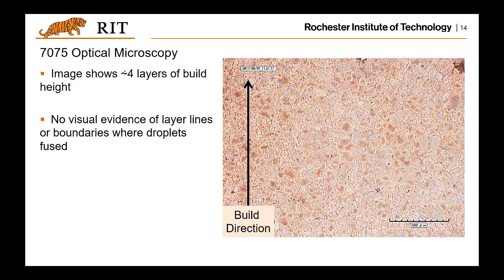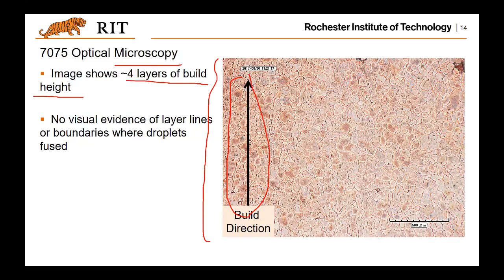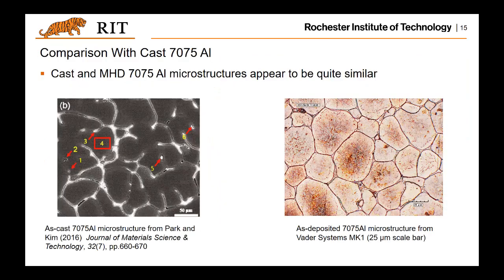And if we look at the macrostructures of the printed layers, this arrow shows you the printing direction. There are 4 layers in the building height, so this is not a single layer. It shows you 4 layers. But from this image, can you tell any interfaces between layers? I don't think so. There are no visible interfaces between the layers. That is desirable, right? That means the different layers are fused quite well, and that leads to a uniform microstructure, which is, again, a good property.